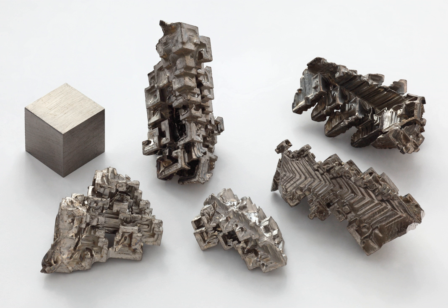crystal systems. When compressed at room temperature, this Bi-I structure changes first to the monoclinic Bi-II at 2.55 GPa, then to the tetragonal Bi-III at 2.7 GPa, and finally to the body-centered cubic Bi-IV at 7.7 GPa. The corresponding transitions can be monitored via changes in electrical conductivity. They are rather reproducible and abrupt, and are therefore used for calibration of high-pressure equipment.